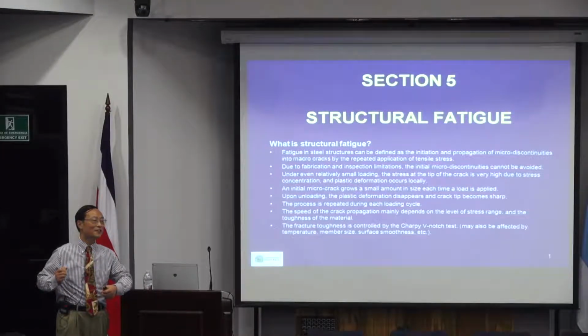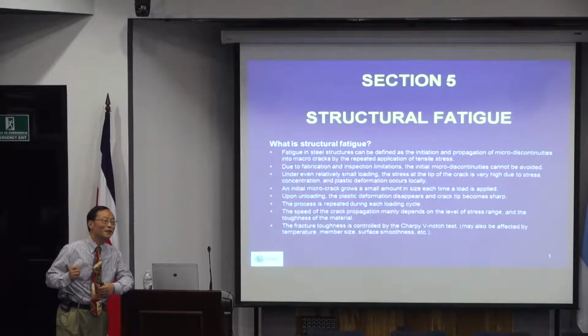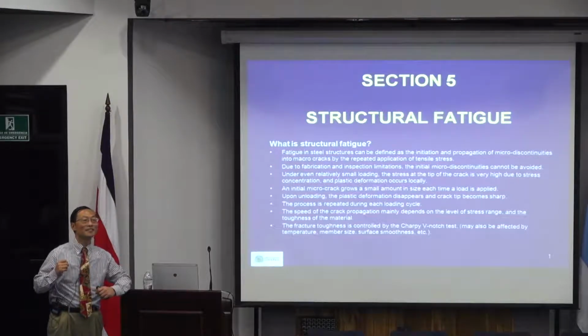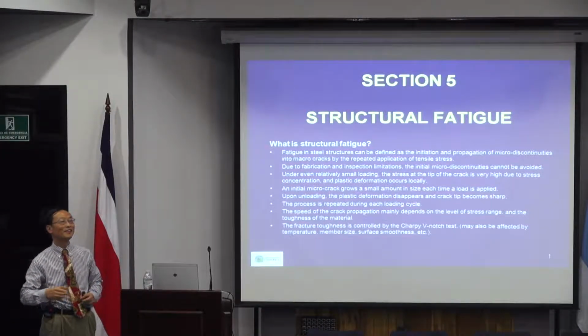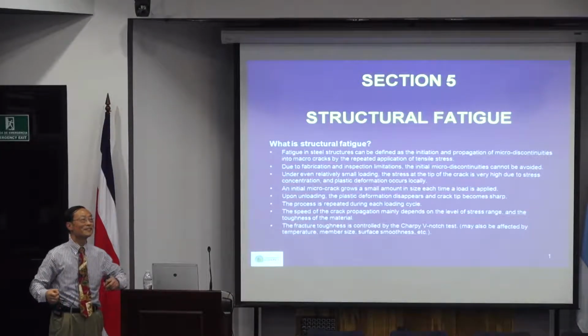So most people now think that fatigue is actually a phenomenon of accumulation of energy. In other words, if you apply a load and release, and apply a load and release, although we consider steel an elastic material, every time you have such a process, a very tiny fraction of energy is lost for that whole process. That loss of energy is absorbed by that defect zone. So in other words, it is the total accumulation of energy that causes the problem. That's why fatigue is a very slow growing process.